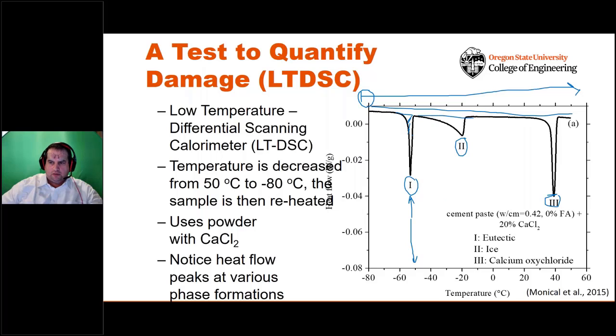The second peak that we see, or the second divot that we see in this curve, is simply ice. This is the amount of ice, and it's going from an ice solid back over to liquid water. It happens slowly over time because of that ice cube effect that I mentioned before, right? Quantify the amount of ice in the system.